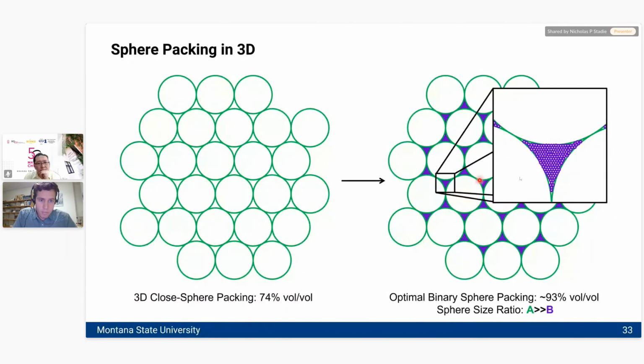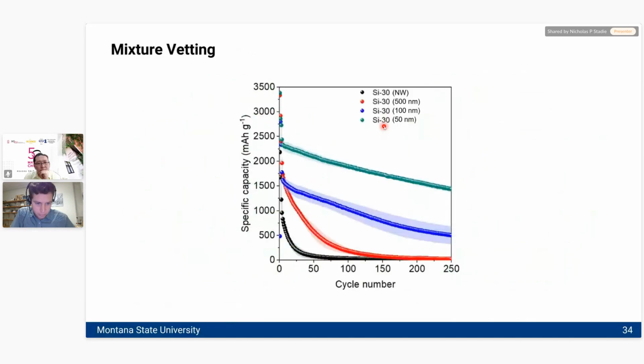And it gave me this kind of picture that when we were packing in 30% of the 50 nanometer particles with 70% micron sized particles, we were probably making some kind of nearly perfect amount of glue in between the interstitial voids of the 1 micron particles, and that may be the reason why the optimal combination is a 30-70 mixture. There's no evidence of that, it's purely speculation.